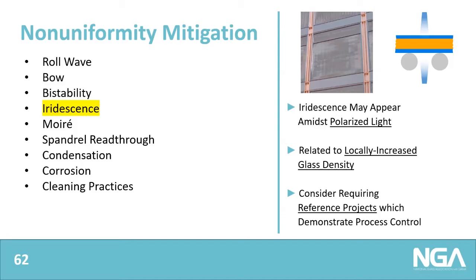Again, it's correlated with polarized light, and in terms of physics, it's attributable to the localized increase in the glass density where the quenching occurs. So the quenching blows cool air onto the glass, that slightly increases the glass density, inconsequentially really for any attribute, except for this phenomenon of the light transferring through the glass, possibly leading to these optics. Iridescence is not a cause for rejection, but if there are concerns about the issue, then a project team may want to reference some recent projects that illustrate the process controls.